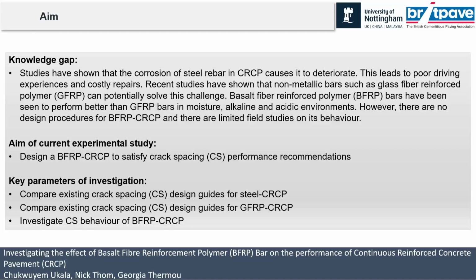Currently, recent research has shown glass fiber bars have been used recently as a replacement for steel. However, research is showing that glass fiber bars don't perform as well as basalt bars when they are in alkaline environments, which we expect them to be in, or acidic environments if they come in contact with acid, or even moisture if some ingression of moisture comes in contact with them while in the concrete. They don't perform as well as basalt bars. So research has shown that basalt bar performs better, but currently they have been using glass bars.